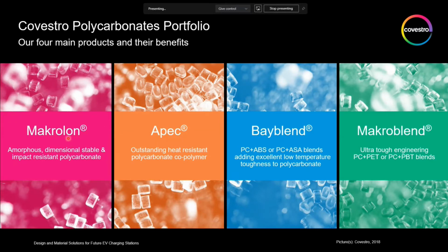If you take Makrolon and you put in a polyester, you get Makroblend. That gives you toughness, and as polyesters are very good in chemical resistance, the takeaway for Makroblend is typically you get very good chemical resistance. So those are the four lines we'll be focusing on during this presentation.